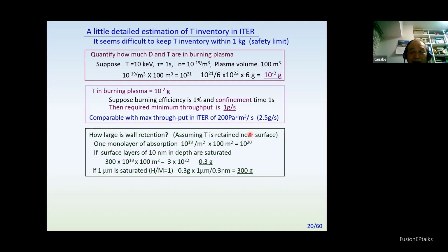How large will the retention be? Assume that T is only retained near the surface, so one monolayer absorption means 10^18 per area, times 100 square meters area, meaning it needs about 10^20 tritium. If the surface layer is saturated to 10 nanometers in depth, that comes to 0.3 gram.